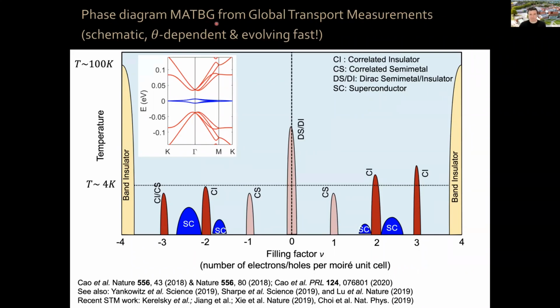So this is the first diagram that one can obtain from global transport measurements, okay? Don't pay too much attention to the details. It's schematic, it's twist angle dependent, and it's evolving quite fast, okay? But let's say overall, what you see is a temperature versus filling factor, this is charge density normalized. So this filling factor nu is telling you the number of electrons or holes per Moiré unit cell, okay? So we typically show this from -4 to 4. It turns out these flat bands can contain up to 8 electrons per Moiré unit cell. So you go from charge neutrality down to the bottom, you go 4 holes per Moiré unit cell.